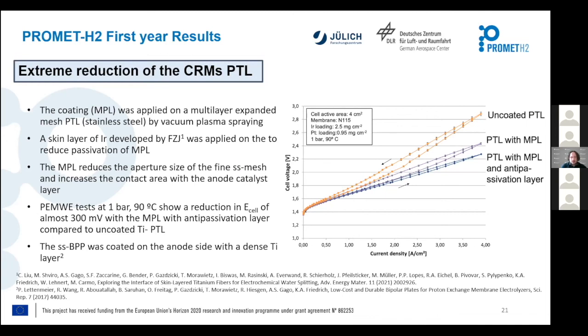In this case, we are producing the coating of the microporous layer, and we use stainless steel PTLs, and we will cover them with MPL coating with a vacuum plasma sprayer. In some of them, the last one, Jülich developed or applied a very, very thin layer of critical raw material in order to reduce the passivation.